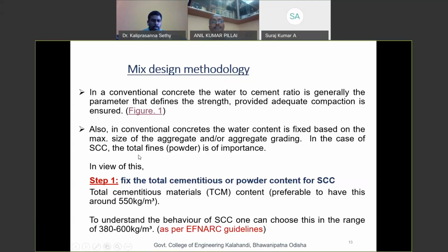And also in conventional concrete, the water content is fixed based on the maximum size of aggregate, say 186, I think, for 20 mm aggregate, and aggregate grading. In the case of self-compacting concrete, the total fines, that is the powder content, is of importance. First we have to fix the powder content, then only proceed to the other materials. In view of this, we came up with step 1, that is fixing the total cementitious or powder content for SCC.